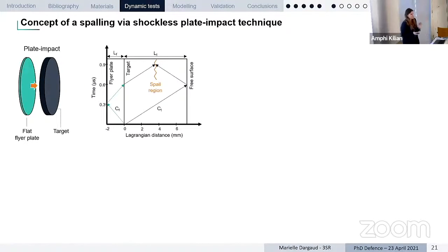Basically, in the plate impact test, we have a fly plate, which is going to be the projectile, let's say, and the target. We are going to launch this fly plate, and the contact with the target is going to generate compressive waves in both materials in opposite directions, and they are going to be reflected at the free surface of both materials. The overlap of the two release waves is going to generate a tensile loading in the material, which can cause the spall failure in the material.